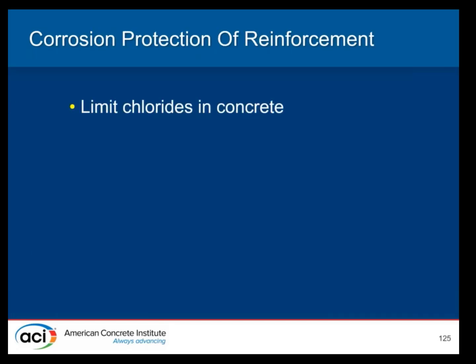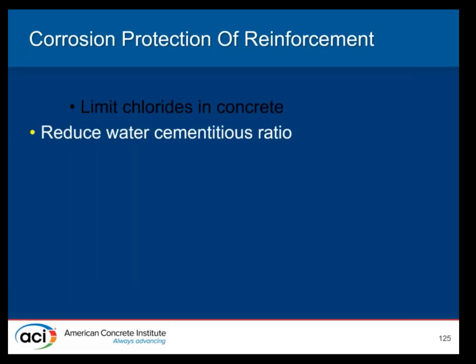So how do we keep our concrete safe from chlorides and carbonation? Obviously, we want to limit the chlorides in our concrete, so make sure we're not using things like calcium chloride as an accelerator or making sure our aggregates are not accidentally contaminated. Reducing the water cementitious materials ratio, trying to create a less permeable concrete, so we're not allowing water in as freely.